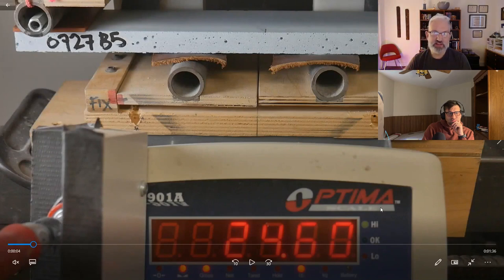This is a 7-day strength, not a 28-day strength. It's a higher water cement ratio: this is 0.3, and the other one was 0.24. So you would think, okay, it's younger, it's got more water, and what are the rules of water cement ratios, right? Higher water content, bad.